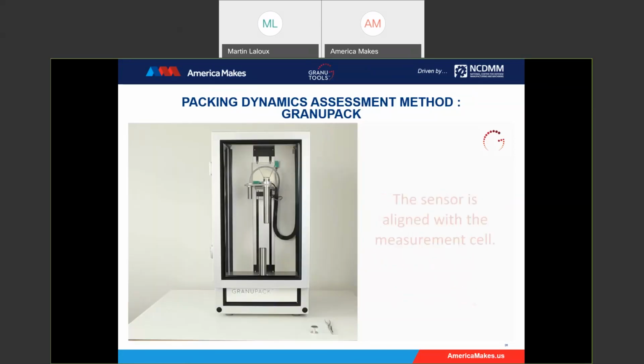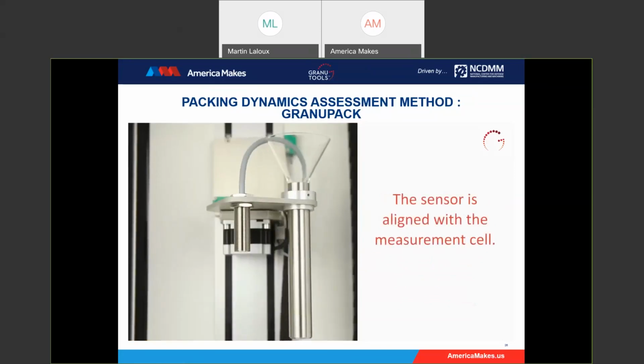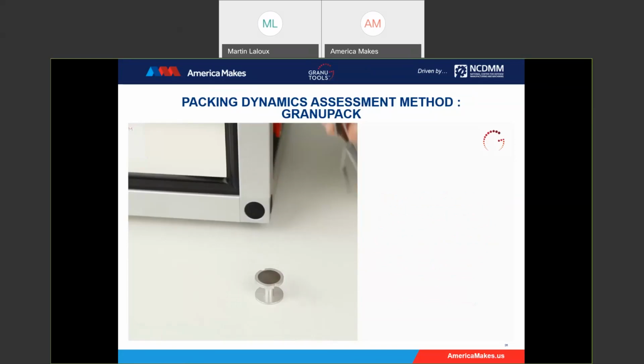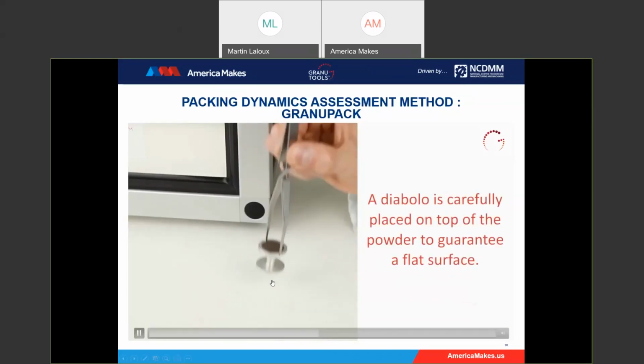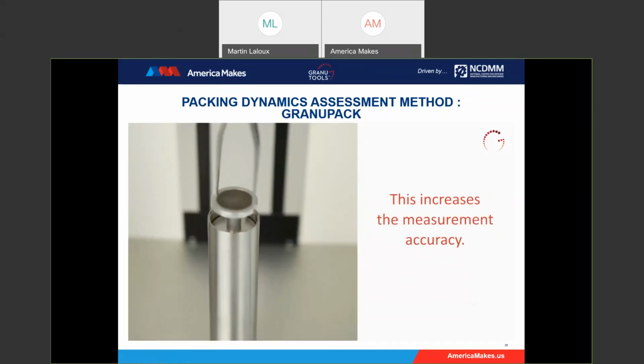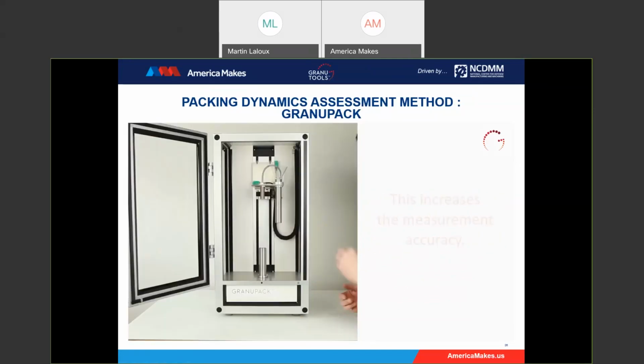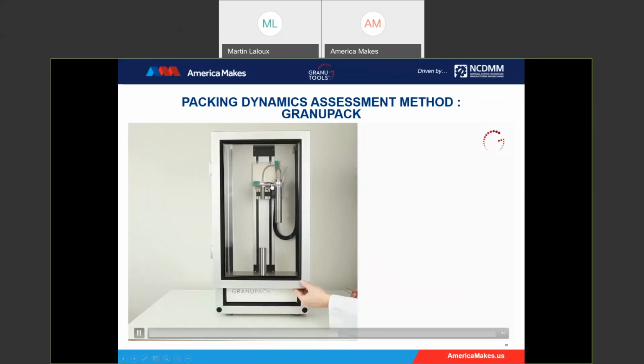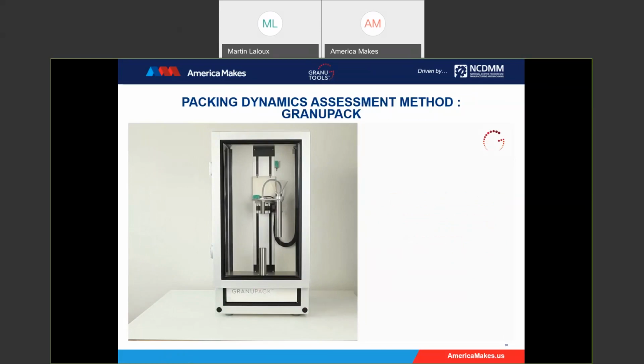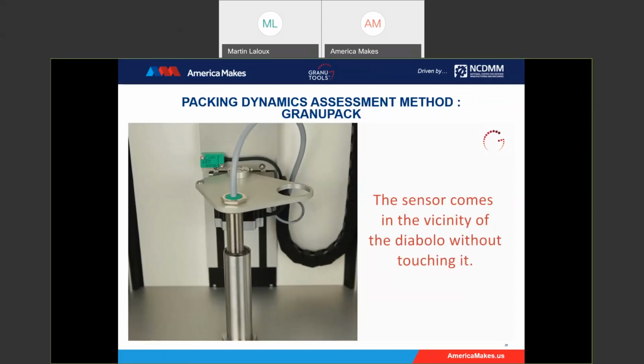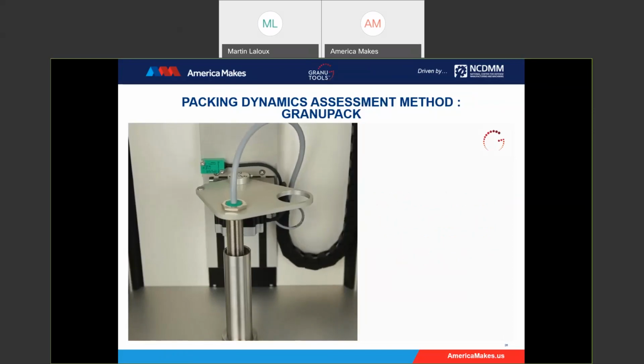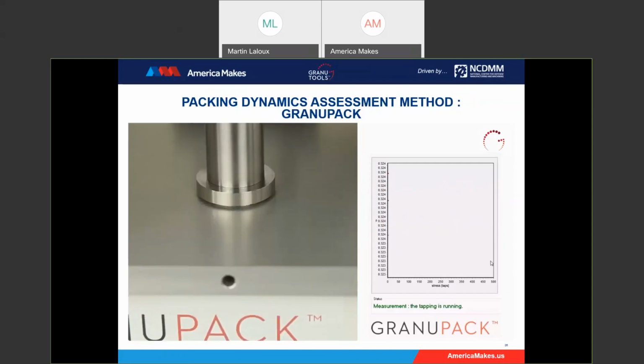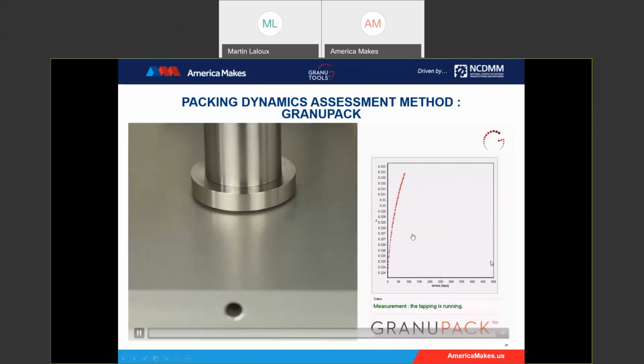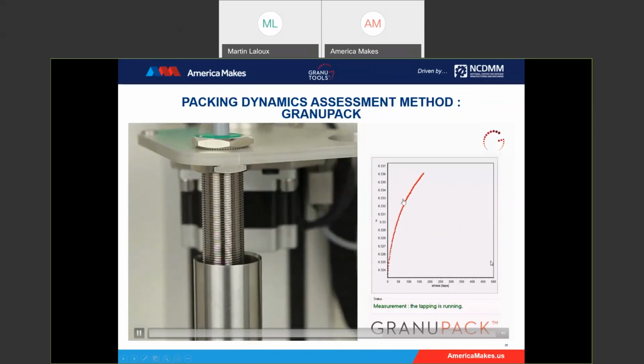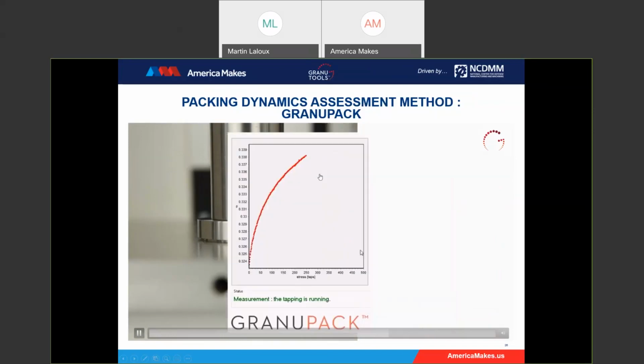After that, we will put a small piece of metal. This is our trick to increase, in fact, the accuracy of the sensor. This piece of metal has a small impact on the bulk density, but as it is the same operator each time, with this impact. And then the sensor will go down without touching this small piece of metal. And then we start tapping. We do 500 taps, and after each tap, we measure the density. As you can see on the right, this is the software. We measure the density after each tap, and so you see all the packing dynamic of the powder.